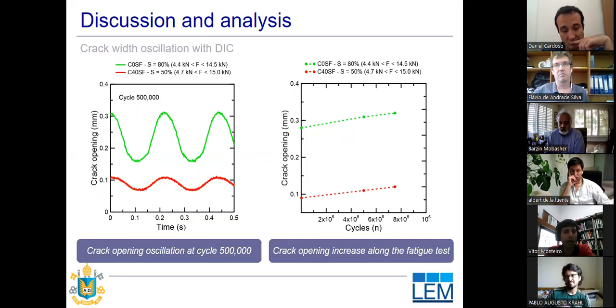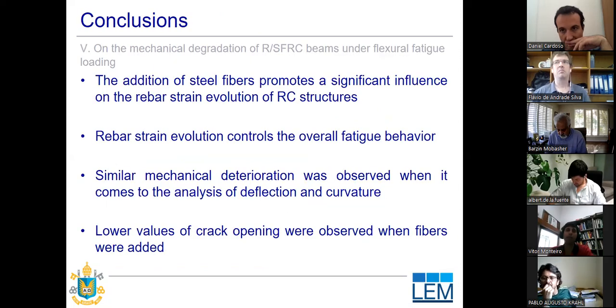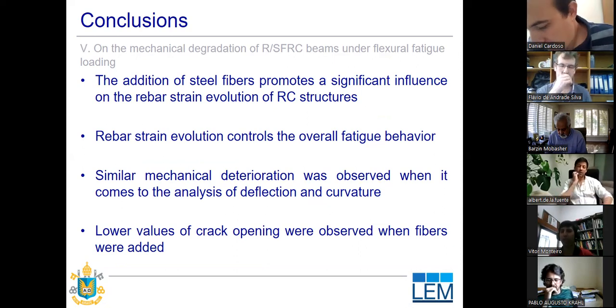So here we have the cracks evolving along the test. Once again, the redistribution of stresses with the fibers is diminishing the crack width along the fatigue test. So the fibers were successful in mitigating the crack propagation evolution on the structural beams. One of the main conclusions in this last section is that the rebar strain evolution controlled the overall fatigue behavior of the beam.